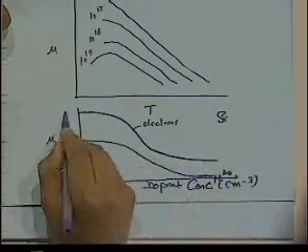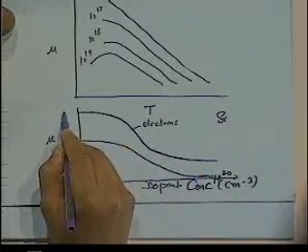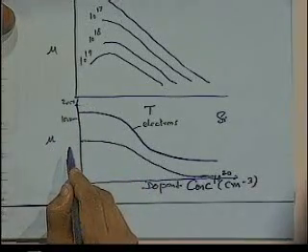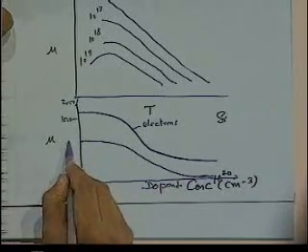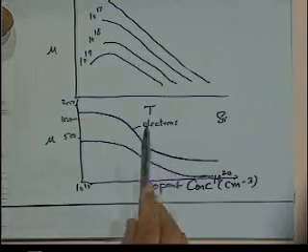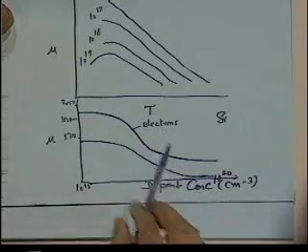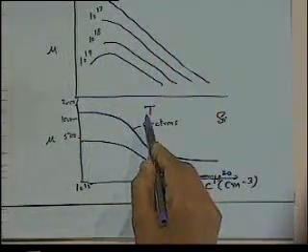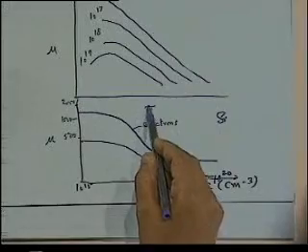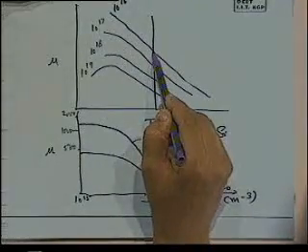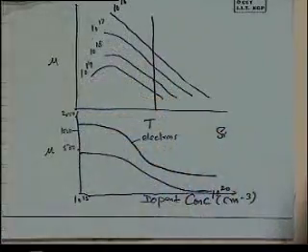As we increase the carrier concentration, the mobility drops. Beyond about 10 to the power 17, it is predominantly influenced by the impurity concentration rather than lattice scattering. This is room temperature data — it's like taking a cross-section at room temperature from the previous temperature-dependent plot and checking how mobility changes with carrier concentration from 10 to the power 15 to 10 to the power 20.